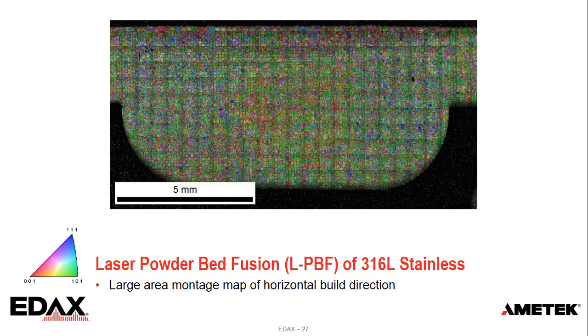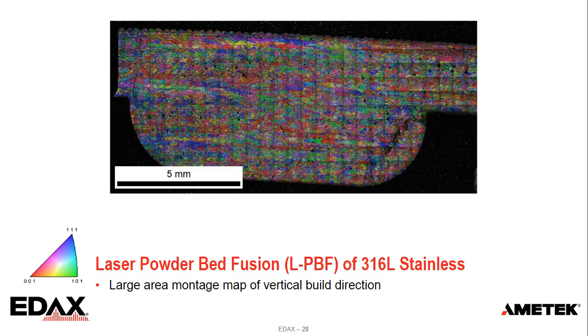Whereas if I compare that to what's termed the vertical build direction, this is where the build plane passed left to right, not out of the plane of the surface for this particular sample. If we look at those, you can see the shape of these two samples is essentially the same, but they were built in two different directions. And that's important because if you were to look at a part and they look the same, you wouldn't realize that the mechanical properties are actually defined by the microstructure. If the microstructure is different from one to the other relative to the shape of the part and the directionality of an applied load, you can get very different performance. And that, I think, sparks some of the interest in understanding the microstructure of these 3D printed parts.